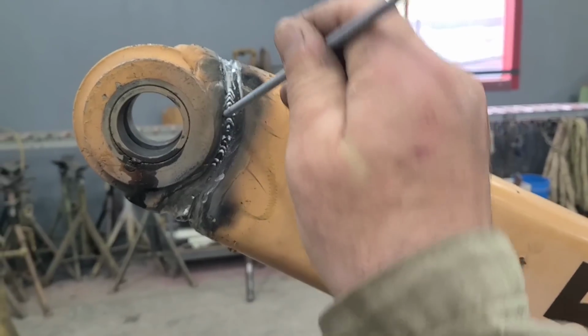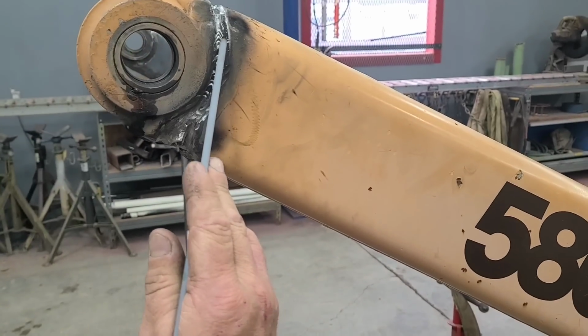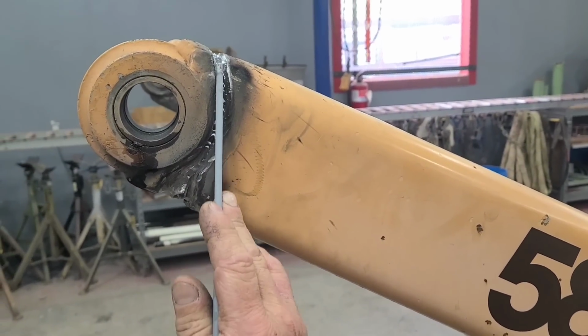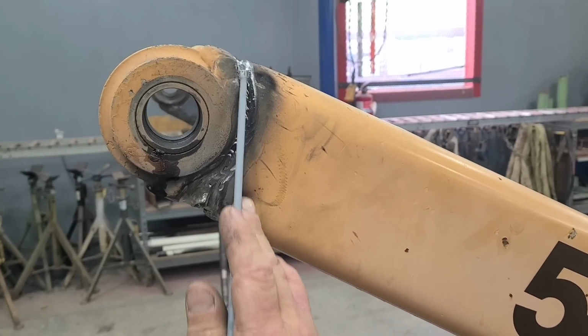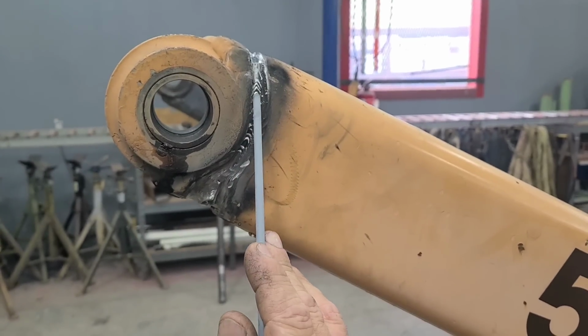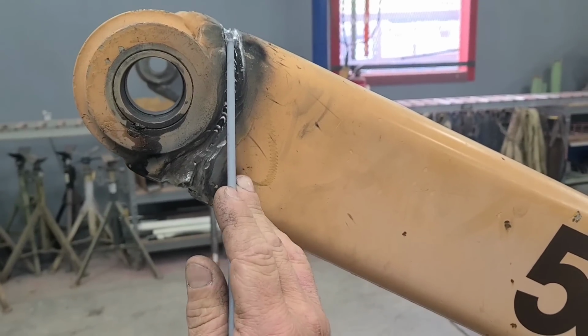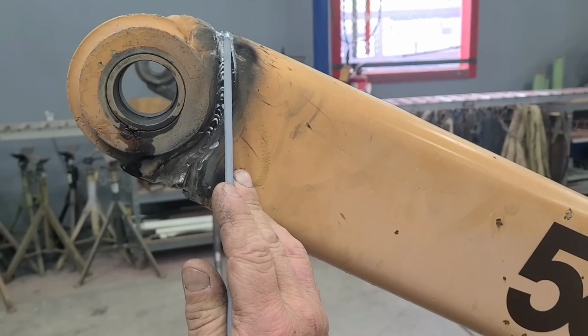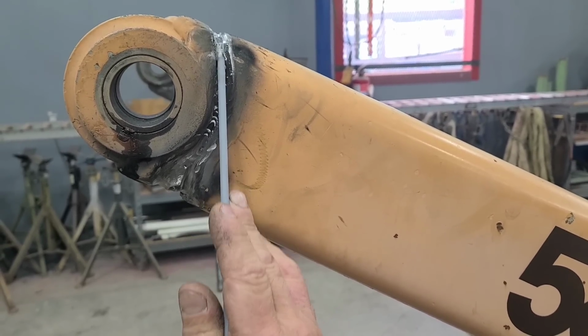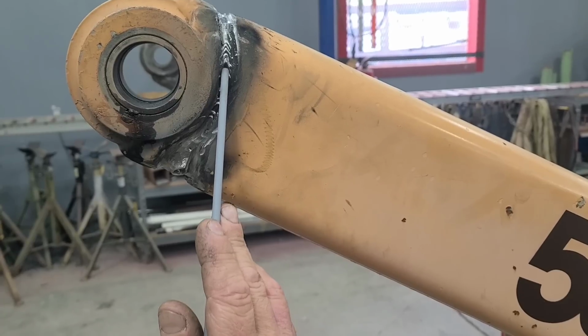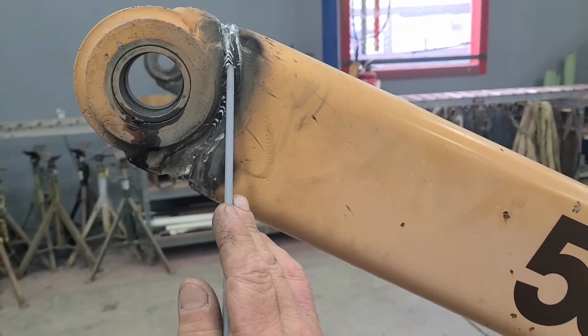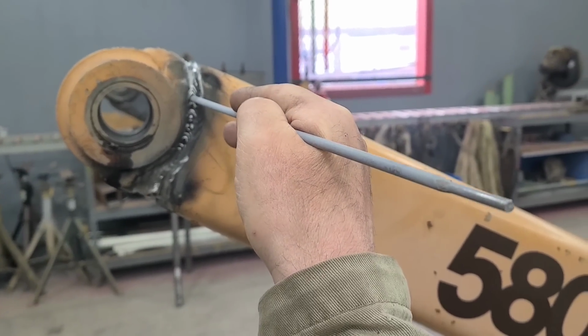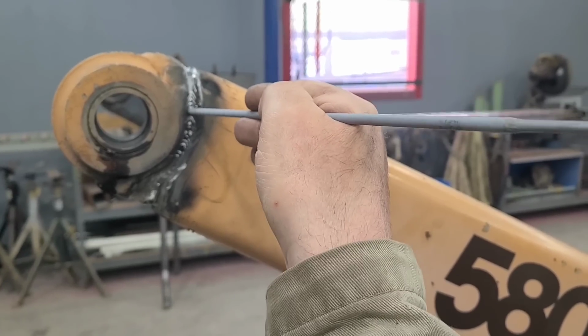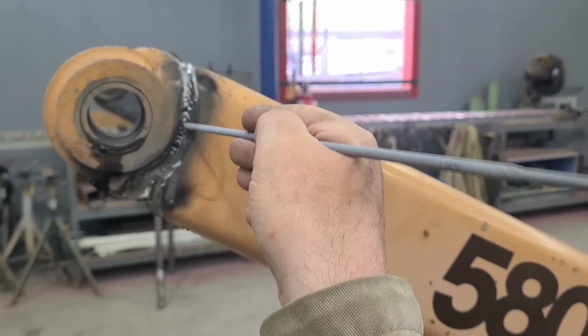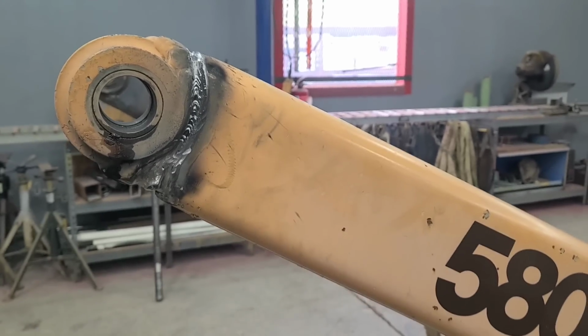Now, the way I get a tremendous amount of heat control with this pipe rod is when I lay this rod down and scratch like this, it blows a lot of the heat forward somewhat. If I start out like this, I have a tremendous amount of amps on the rod, and I start out with this rod on this steep angle. When I see that I need more heat into the metal, all I got to do is change the angle of the rod. And if I get to the point where I'm holding the rod 90 degrees from the material, then the penetration is extremely deep.